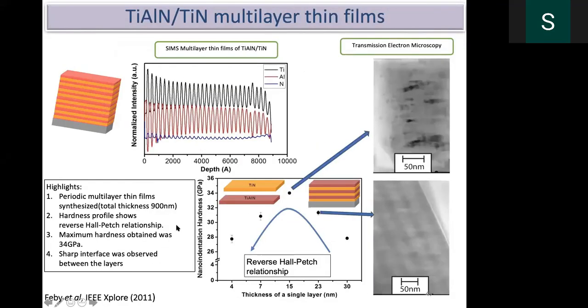From this, you can understand a multilayer can also show hardness that varies exactly as Hall-Petch and reverse Hall-Petch. This x-axis is the individual layer thickness. This is the transmission electron microscopy. This is SIMS, secondary ion mass spectroscopy. If you change the individual layer thickness, that's what I have shown here. If the single layer is 30 nanometers, the hardness is around 29 GPa. If you reduce it to 23, it goes to 32, and it goes to 34 when it is 15. That's what I wanted to show here.